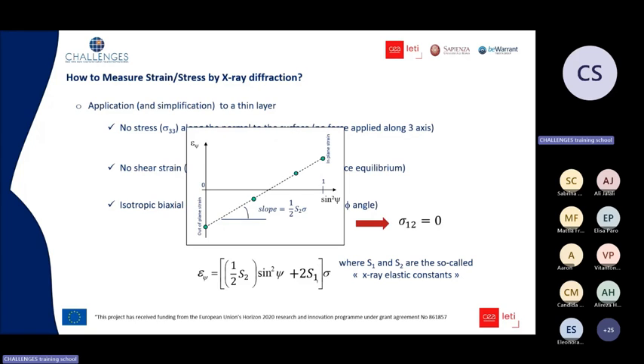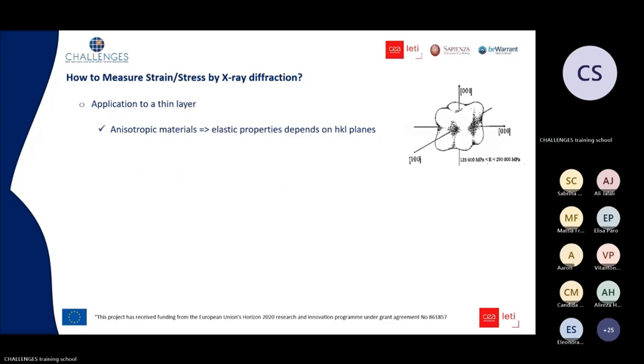What does it mean? It means that if we can measure the strain in at least two directions, but we can measure more than that, of course, the slope of this relationship gives you directly, through the elastic constants of the material, the stress in the layer. So this is what we call the sine square psi method, which is very well known in our field.